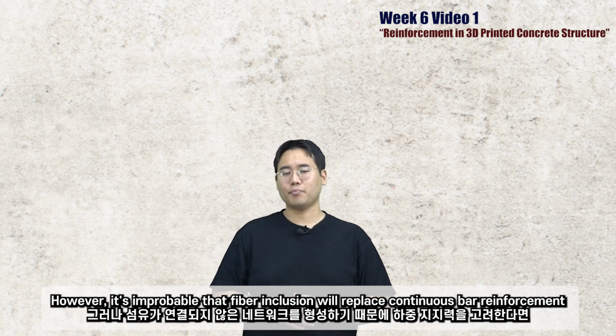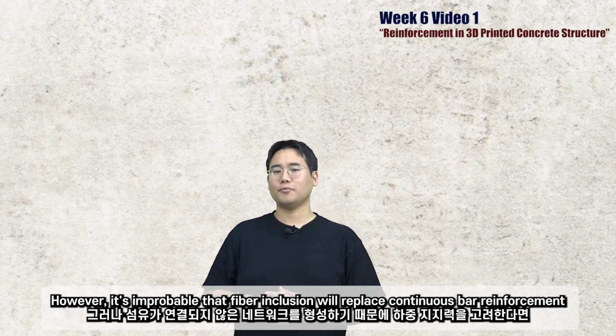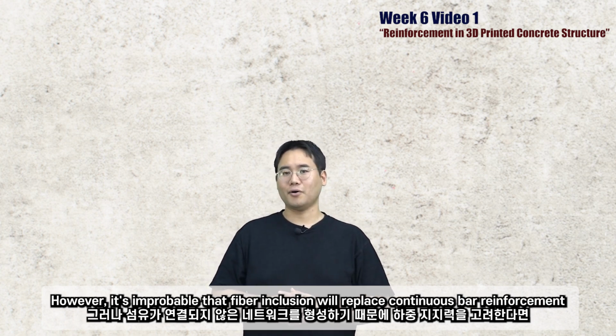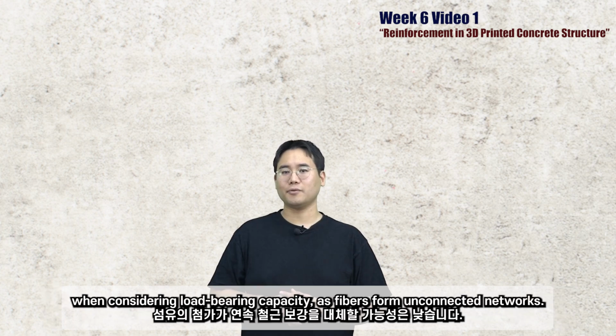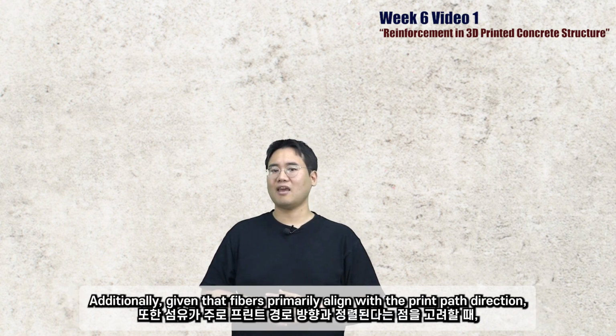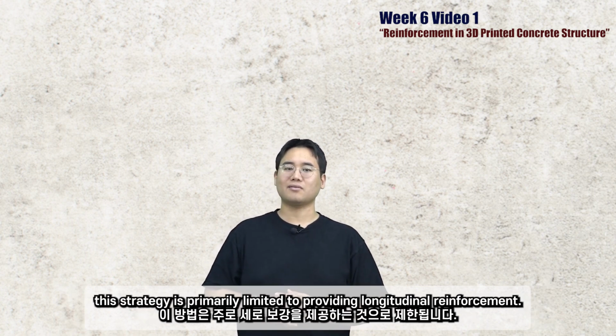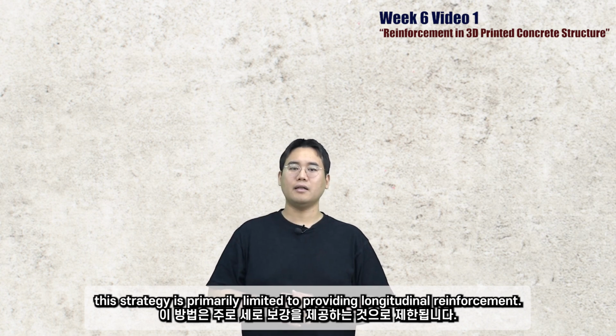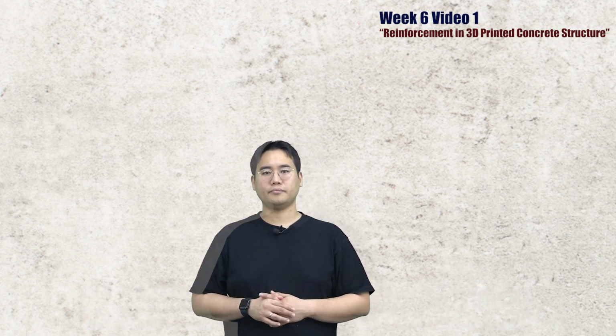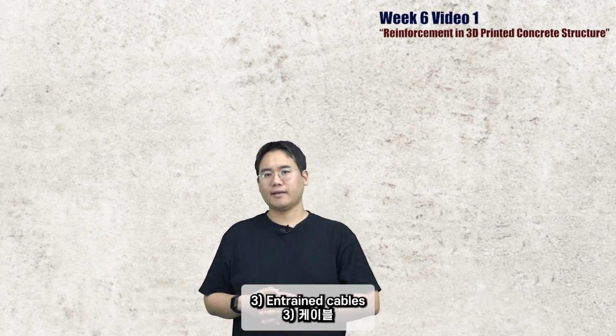As a note, it was found both flexible and stiff fibers preferentially align with the filament flow directions. However, it's improbable that fiber inclusion will replace continuous bar reinforcement when considering load-bearing capacity, as fibers form unconnected networks. Additionally, given that fiber is probably aligned with the print path direction, the strategy is primarily limited to providing longitudinal reinforcement. The next one is cable entrainment.